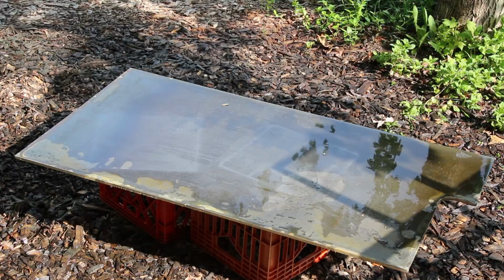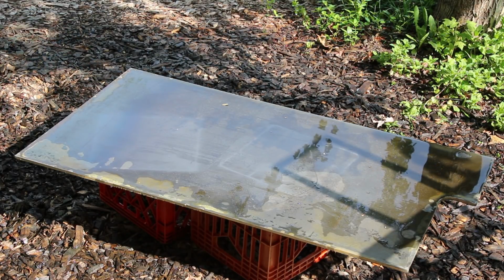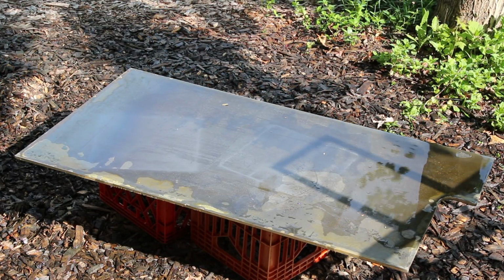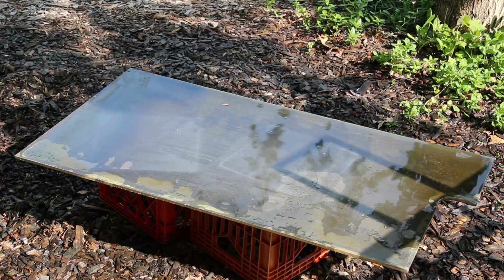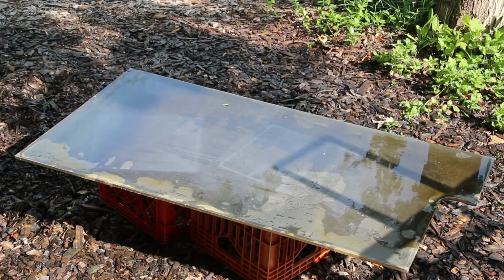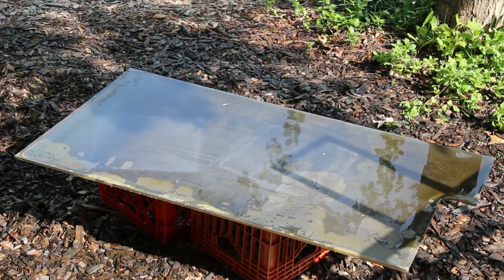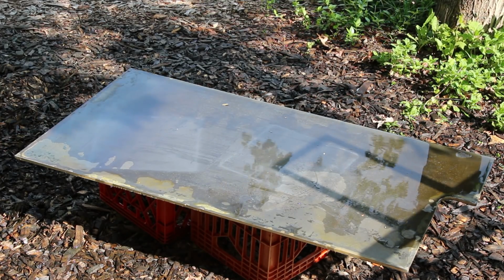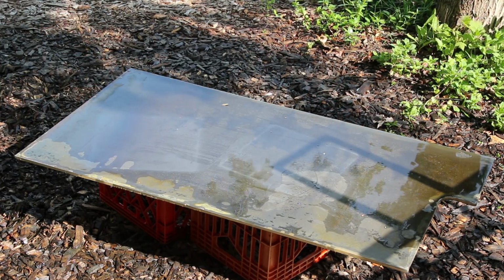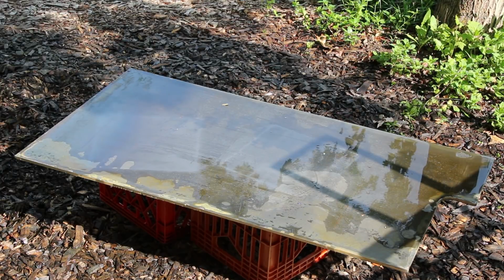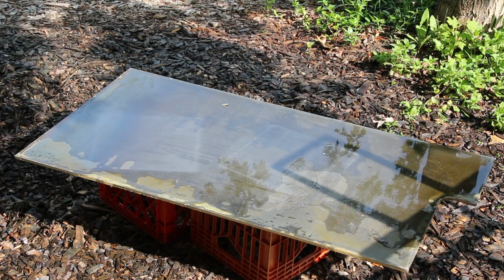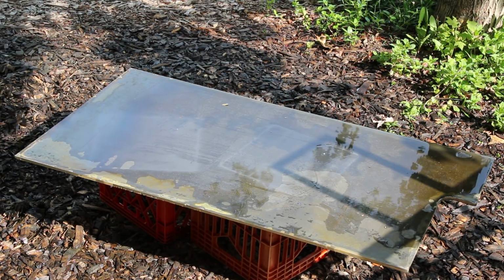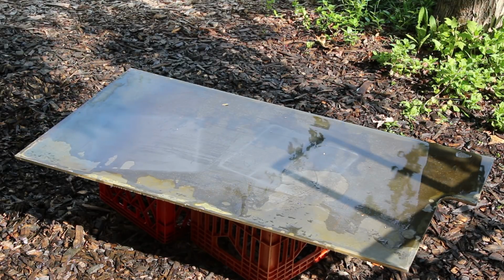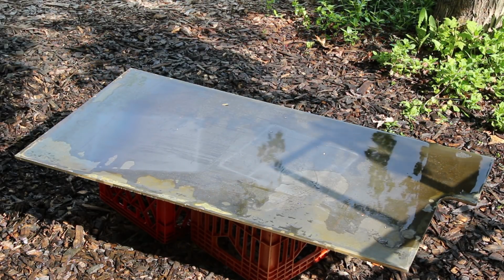My first attempt to remove mill scale from the plate didn't go very well. I applied muriatic acid and I scrubbed and scrubbed and worked at it for about 15 minutes, and the scale was kind of sort of coming off, but largely was not. But eventually I realized that the problem was I had grease on the surface, and so the acid was not really reaching the scale itself in all areas. So that was on the other side of the plate, which will be the bottom.